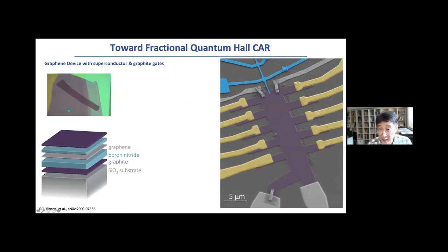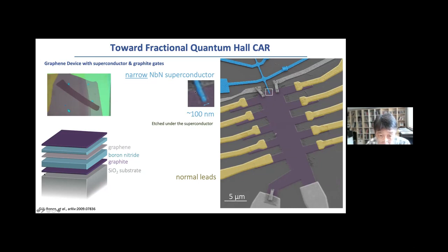It's doable. Here's a device, the overall image, and this is normal. The gold color is a normal contact made of titanium gold, and here the cyan color is the narrow niobium nitride contact. An especially essential part is the end of this niobium nitride contact. Width is about 100 nanometers, even less, right? And then, as I said, the graphene underneath this contact is removed first and backfilled with the niobium nitride. So you can think about this as a trench in the graphene channel backfilled with this superconductor. Another important aspect is we have to carefully etch away this top graphite gate, such that there is a region around this superconducting region where we can separately control the density, which actually plays an important role in the last topic I want to touch upon.